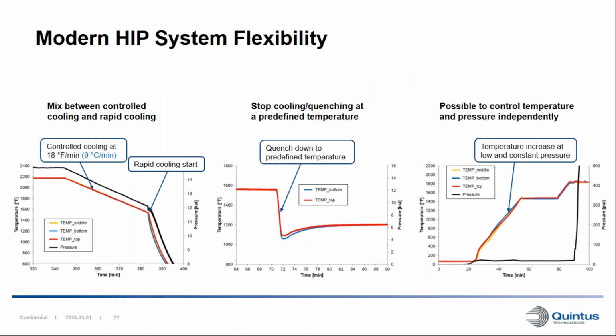Some other flexibilities in these kinds of systems: on the left here, we can see where we can mix between controlled cooling and rapid cooling. In the beginning here, we have a specified cooling rate of 18 Fahrenheit per minute. And at the predefined temperature, we start the rapid cooling and cool the material down fast. In the middle here, we can see where we can actually stop the quenching. We don't need to quench down to room temperature. We can stop the quenching at any temperature, which we have done here. So we can see we have the soak time, we start the quenching, and then we stop it at 1200 degrees Fahrenheit with a slight undershoot, and then it turns into the isothermal temperature.